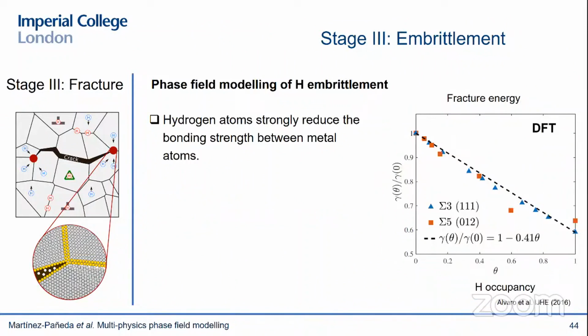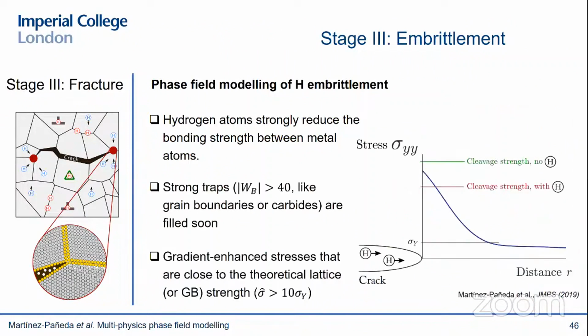And then the next question is, okay, is a 30 to 40% reduction in fracture energy or grain boundary strength sufficient to trigger a shift in failure mode from ductile to brittle? And in my opinion, the answer to that comes if you resolve the critical stresses of the problem over the critical distance. For that, I'm not going to get into details, but we use strain gradient plasticity theories because we know from experiments that the critical distance is a few microns ahead of the crack tip. So you need to resolve the dislocation hardening mechanisms that govern crack tip behavior.